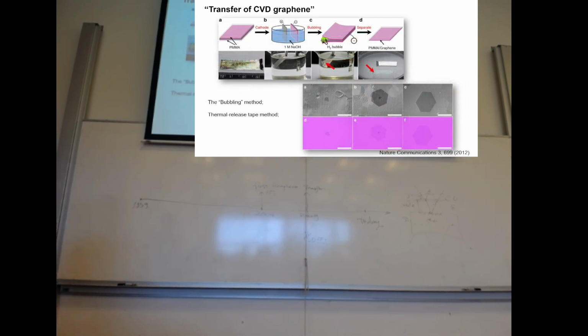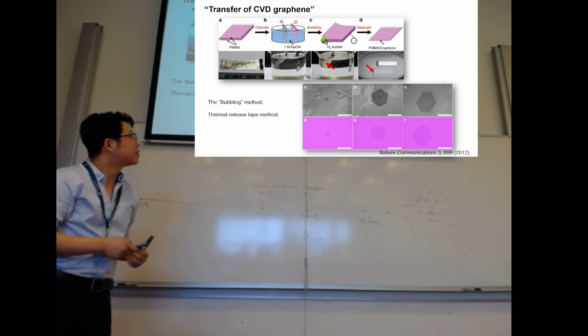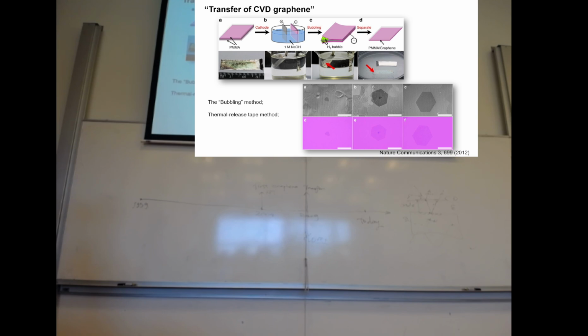And then people wanted to really enhance the method, for example, to create a cleaner way or a faster way. So this is an example in Nature Communications 2012. It's already a little bit later than 2009. We see that people found that if we put an electrode voltage between two metallic plates, one of them is graphene with PMMA coating, the other one is any kind of electrode. Due to these electrochemical reactions, the water will be decomposed into hydrogen gas and oxygen gas. These hydrogen bubbles happen only at the surface of, for example, platinum or copper or anything. If you control how you feed the current and the voltage, you can really get rid of this PMMA graphene layer by just bubbling with this little solvent.